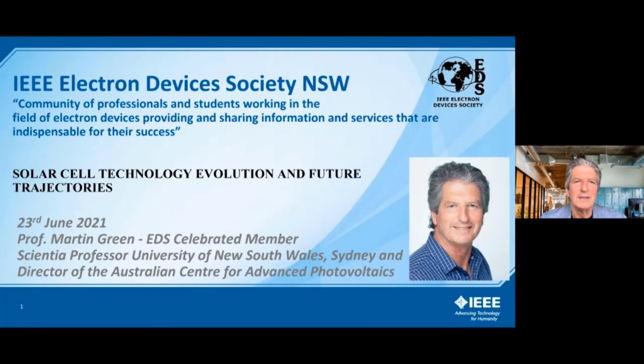Generally the strongest way of mounting a panel is to have the support structures going across the panel. How can I describe this? The panel is an elongated rectangle, and you have the cross members going across the long side of the panels. And that gives you the highest strength. But for a bifacial panel, you generally have the support structures running along the long frame direction of the panel, so that you have nothing running across the rear of the panel. So you use a different mounting structure, which is not quite as good in terms of the loads that the panel can withstand. Panels are rated generally for wind loading as well as snow loading. So they're the two big mechanical loads that the panel sees. But they're plenty strong enough for most environments, even with a non-optimal mounting structure.